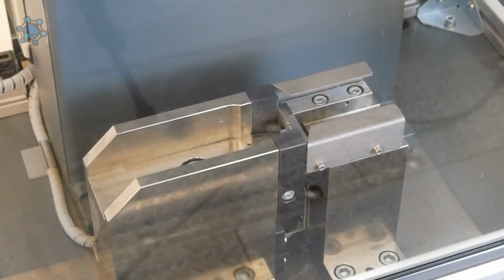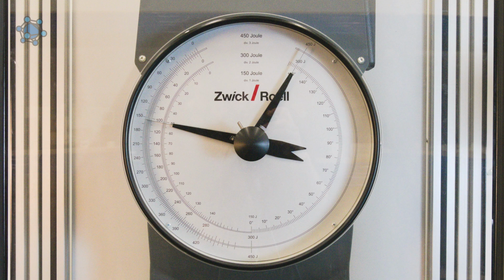The second test is carried out with a V specimen made of 1.4301 material, a type of stainless steel. This specimen is also placed centered in the support of the machine. The display is again set to 0. When the pendulum strikes, you can hear the difference in pitch upon impact from the first test, the second having a significantly lower pitch. The specimen also achieves significantly more notch impact energy, namely 153 joules.